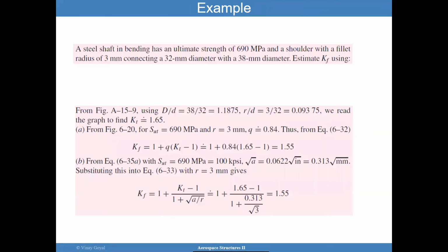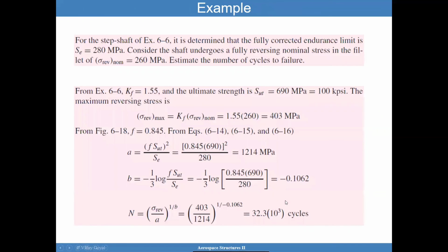And so once you have that, you can calculate KF, and that's 1.55. And then you can use equation 2 and you get the same answer. Once you get that, you can take the nominal stress from your calculations, increase it by 1.55, and then use that to get your fatigue curve, SN curve.